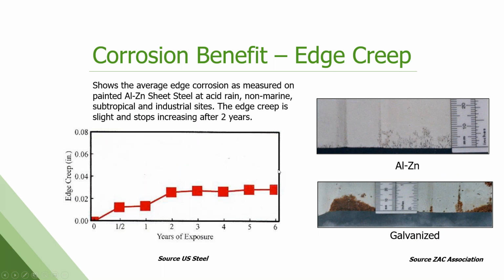Here are some pictures. I think these pictures are better than my graphics. So on the right there is an aluminum zinc panel painted and a galvanized panel painted with the exact same paint systems, exposed in the exact same outdoor setting on a test fence. And you can see the difference there. After a few years, the galvanized is showing some red rust creep. And yeah, you have a little corrosion on the aluminum zinc panel as well on those edges, but not nearly as severe and as dominant as the galvanized.